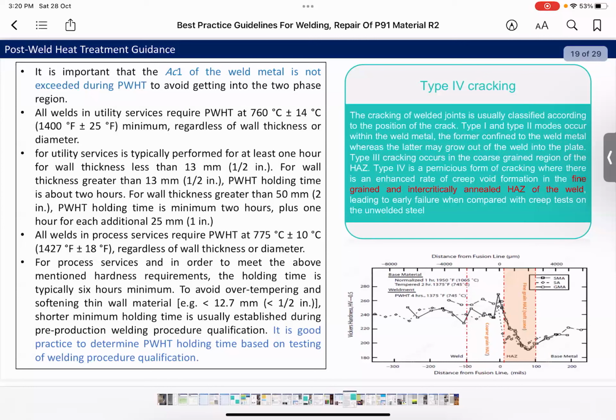Premature failure in P91 material is most of the time attributed to improper PWHT. So it is a good practice to determine PWHT holding time and PWHT temperature on testing of the welding procedure qualification, and that welding procedure qualification should be strictly followed.